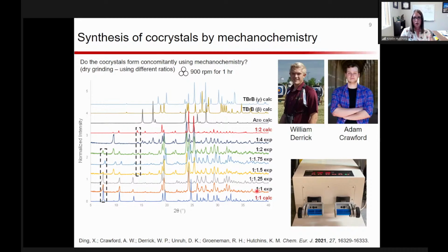So what we decided to do was start with a 1-to-1 ratio and then increase the amount of azopyridine that we were adding in the milling experiment all the way up to a 1-to-4 ratio. In the case of the 1-to-1 and the 1-to-1.25, I've highlighted a key peak in the 1-to-1 form. And you can see here, with these lower ratios where they're almost equal, we get almost exclusively the 1-to-1 form. But once we get a little bit above this, at 1-to-1.5, we start seeing the appearance of the 1-to-2 form. And it's not until we get all the way to a 1-to-4 ratio, where this peak at about 7 degrees 2-theta is absent, that we really get exclusively the 1-to-2 form.